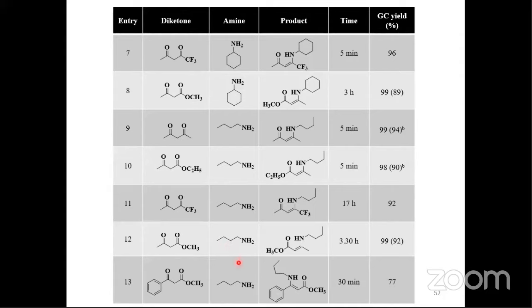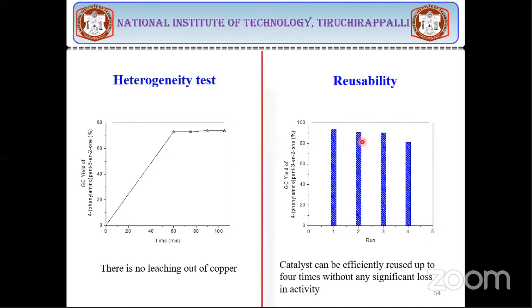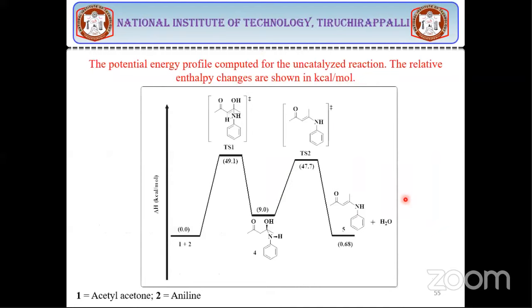You see, different aliphatic amines were combined with beta-diketones to form beta-ketoenamines in very good yields. You see, 99% within 5 minutes, this product was formed. So it's a very efficient catalytic system to prepare beta-ketoenamines, right? And again, we have proved that the reaction is truly heterogeneous. There's no leaching of copper. Of course, there is a slight reduction in the yield when the catalyst is further reused. Maybe the copper becomes copper oxide during the course of the reaction. That might be the reason.